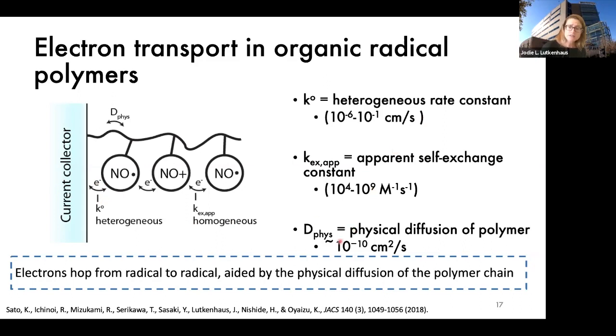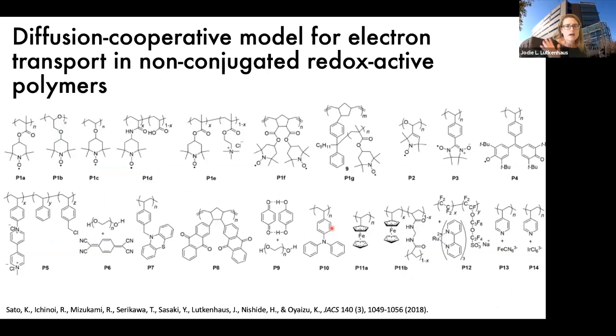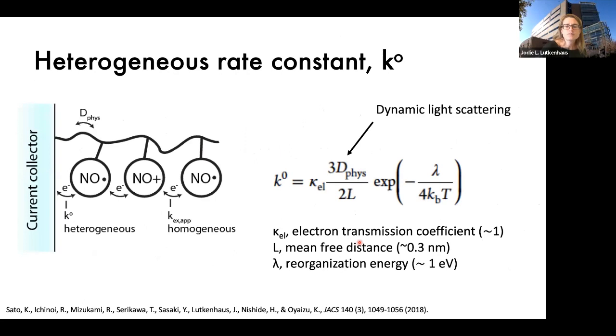And then now we need to consider the physical diffusion constant of the polymer, which Kahn got through light scattering, but there are certainly other ways to do it. This is a whole series of polymers that he brought over from Waseda University. So you can see the top row consists of a lot of nitroxide radicals, and the bottom row also contains redox-active groups on these non-conjugated chains. So experimentally, he was looking at these different polymers.